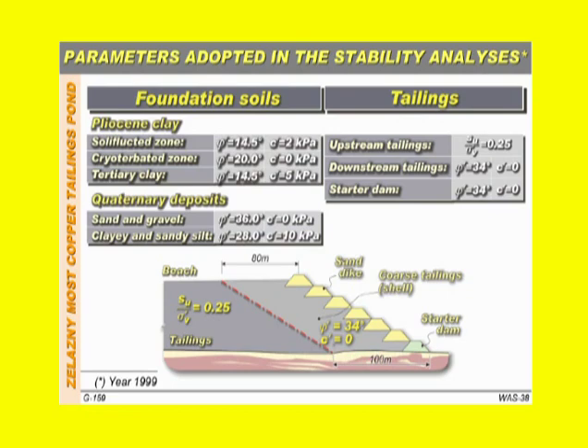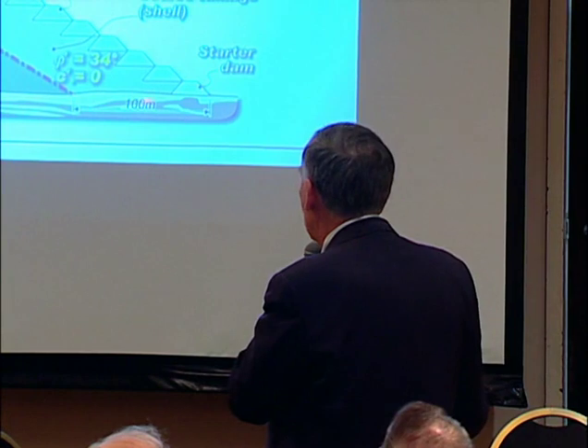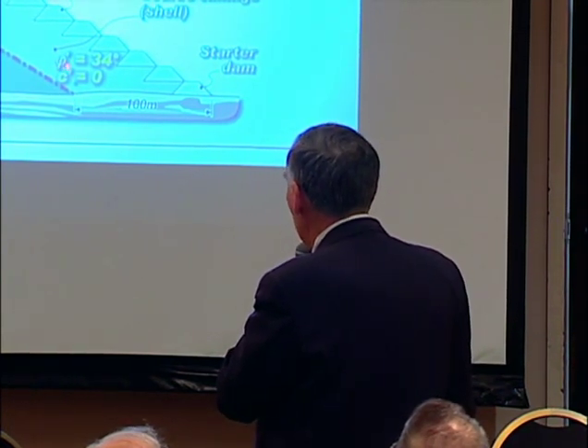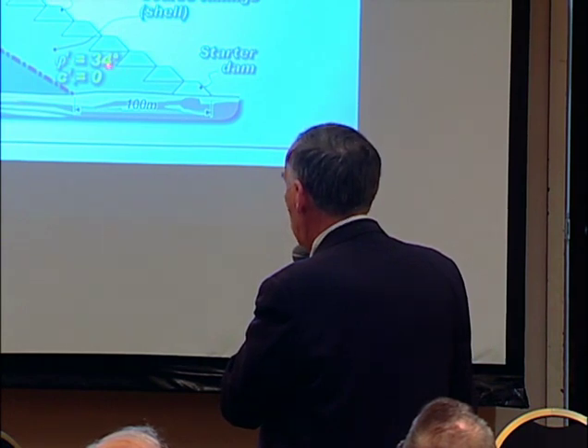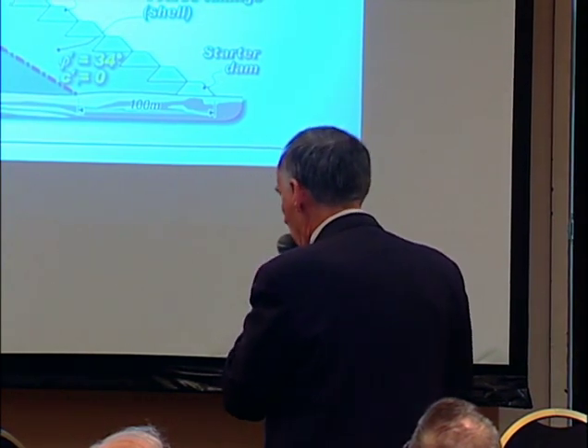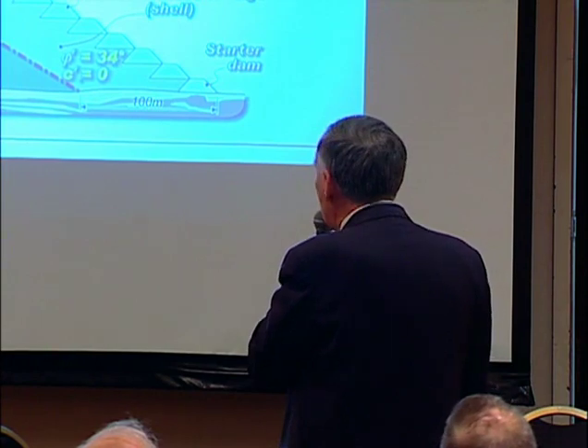For the tailings, despite this experience with the undisturbed samples, we stay very conservative. For upstream tailings, we have S_u over sigma prime v of 0.25, which is much lower than the same value at the phase transformation. And this part of tailings is fully drained because of different toe drains and so on. For tailings, we have phi prime 34 degrees and c prime obviously 0. This is very close to the friction angle at critical state. The next.